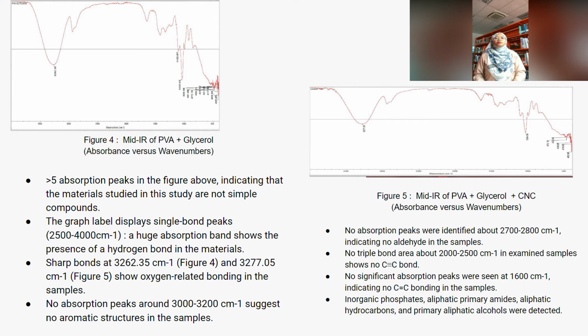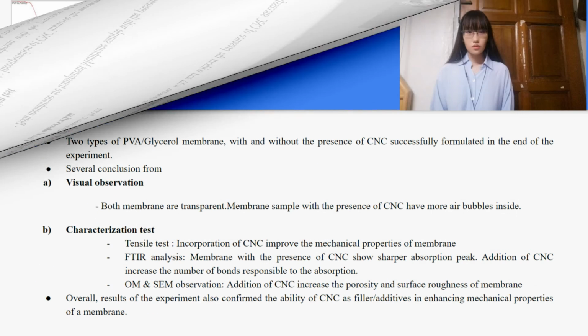Because there is no triple bond area between 2000 and 2500, there is no possibility of a carbon triple bond existing in the samples that were analyzed. There was no evidence of C=C double bonding in the samples based on the observations that there were no substantial absorption peaks at 1600. It was discovered that there were primary aliphatic alcohols, inorganic phosphates, aliphatic primary amides, and aliphatic hydrocarbons.